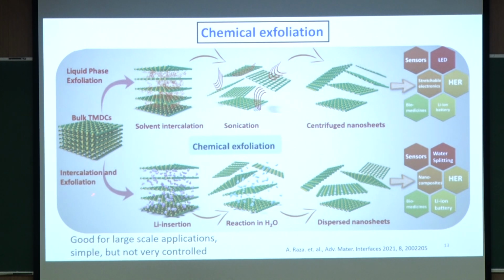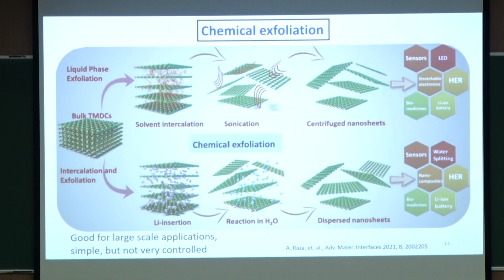Or you can also use intercalation, where you intercalate lithium, and lithium is just one example. You can intercalate with the lithium and then react with water, and again you can get this kind of dispersed nanosheet. The great advantage is that it's very good for large area applications. You'll get that ink and you can paint it.